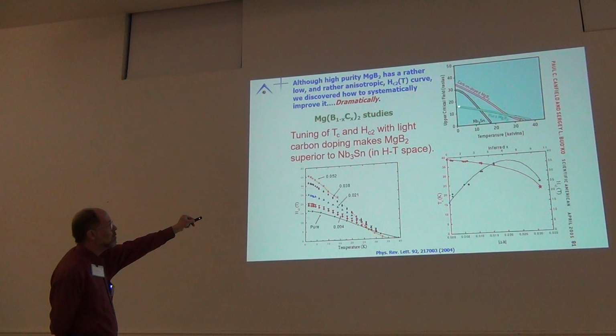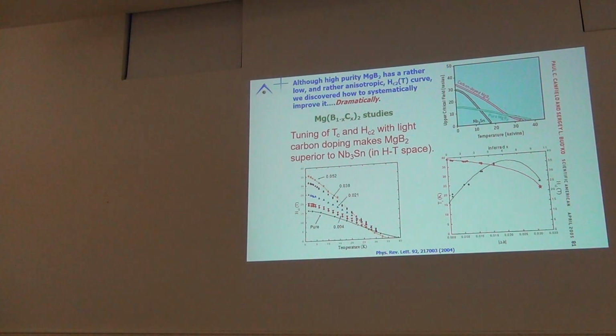Now, with a very pure BCS superconductor, in some cases you can actually improve HC2 by shortening the electronic mean free path. We were able to do that by adding carbon. With carbon, we weakly suppress TC from around 40 to around 35, but HC2 goes from 15 to 20 to 25 to 30 to 35. Okay? For 5% carbon substitution, we can have bulk superconductor that supersedes niobium-3tin at all temperatures. Okay? And this is significant because since 2001 or 2004, where we were able to do this optimization, over the next decade, MgB2 has gone from, my goodness, what is that, to, yeah, and we're making stuff with it.